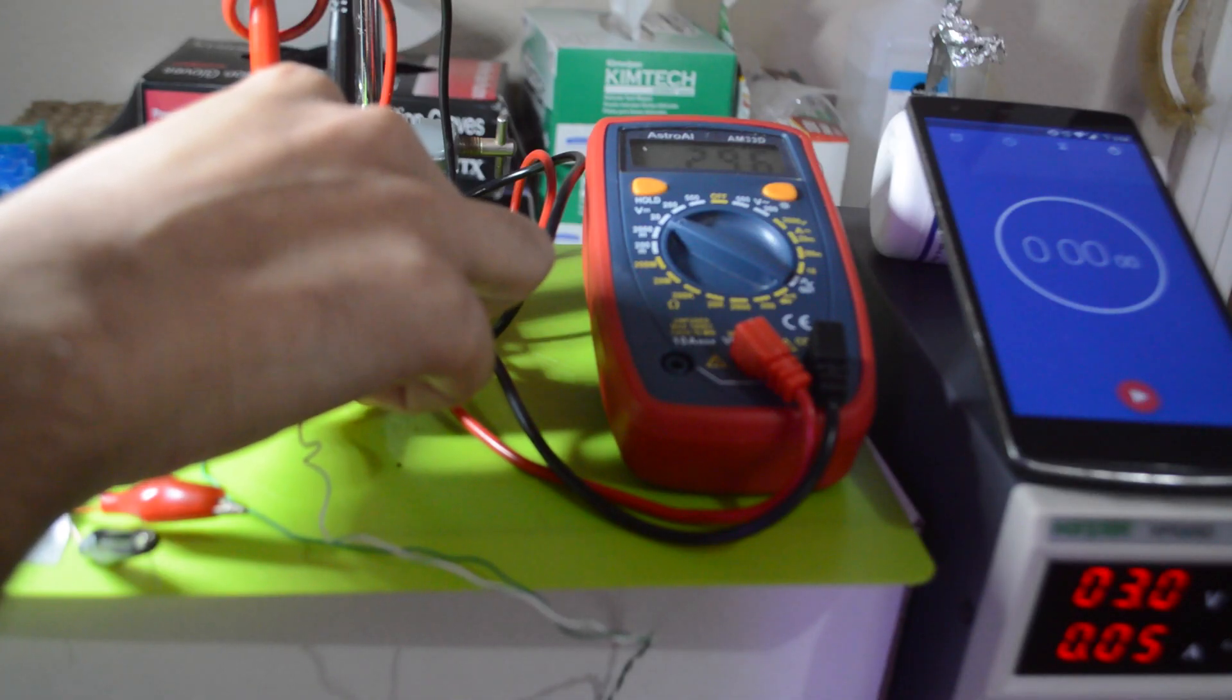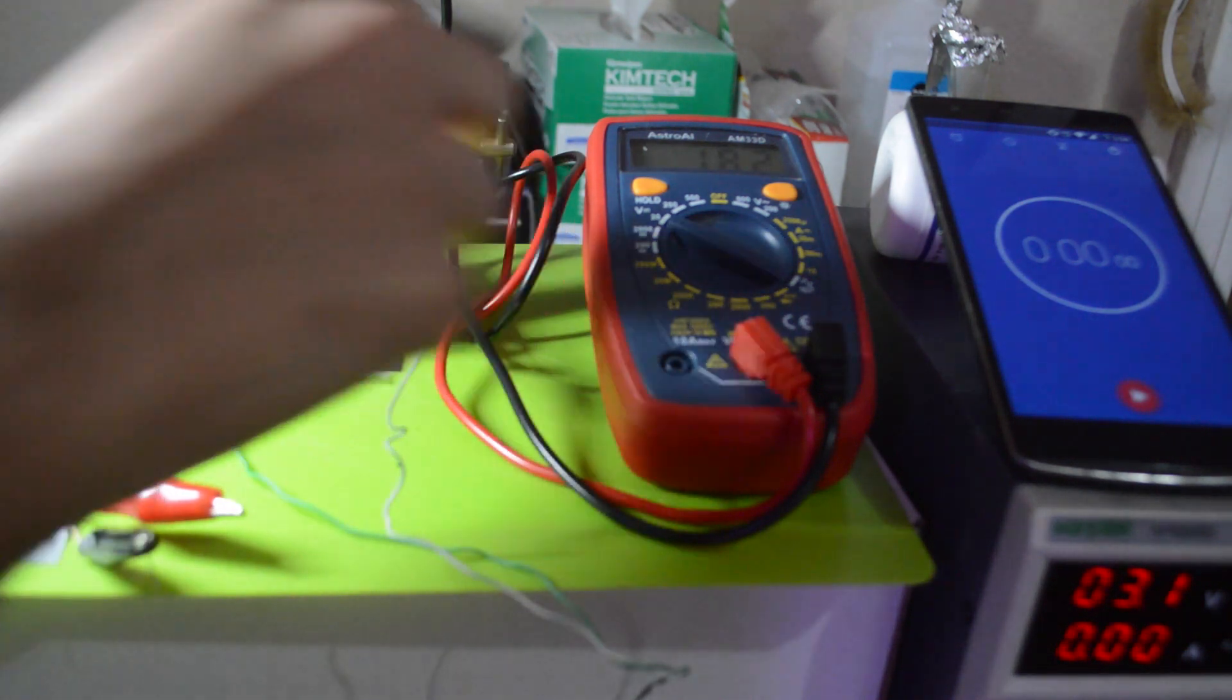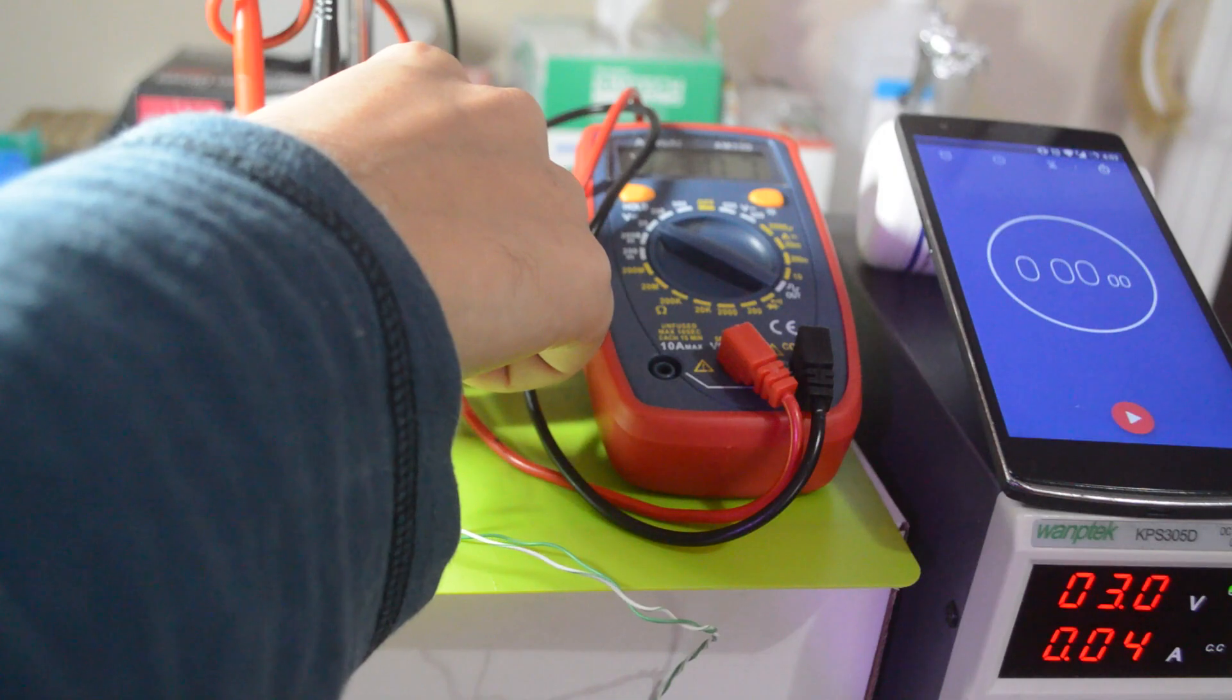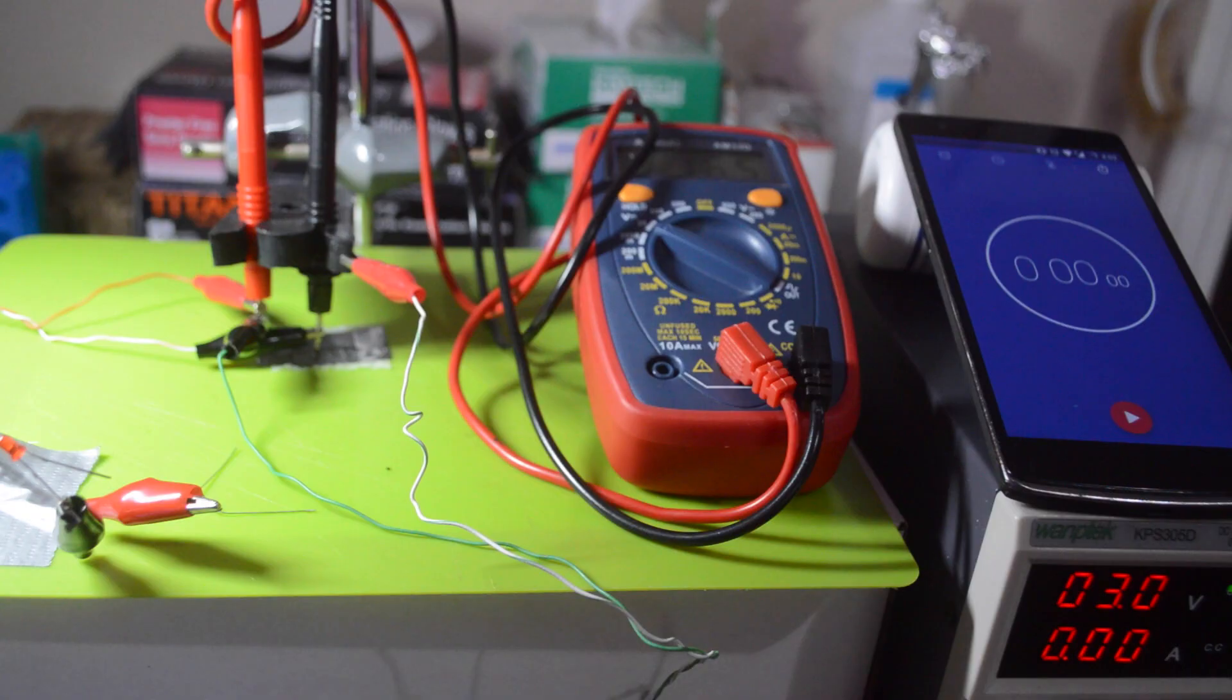Let's try this with our test cells. First up, the phosphoric acid. I'm charging the cells with 3 volts and 1 amp, which is technically a little bit high and may damage the electrolyte a little bit. First the peak voltage. You'll notice it doesn't really sit at a number and drops off pretty quickly. Let's do that again with the sodium sulfate. This time it's much slower to drop, but again it doesn't really sit anywhere for too long. This is because of the low capacitance of the cells and internal leakage. But of the two, the sodium sulfate was better.